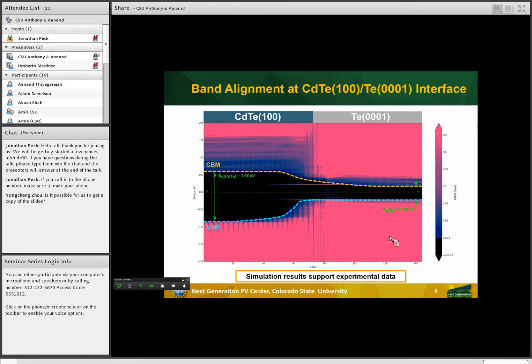This is the band alignment of the CdTe 100 tellurium interface, and it's very much different compared to the CdTe 111 tellurium interface. There are not as many prominent states that exist in the tellurium band gap as in the previous model, and also the conduction band doesn't bend upward as presented in the previous model. The lack of an upward bend may lead to recombinations at the back of the device. However, experimental data shows us that cadmium telluride preferentially orients along the 111 plane. So this model would just be a small fraction of what's seen in polycrystalline CdTe.